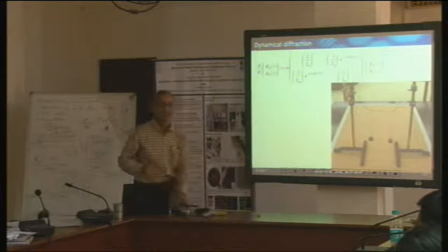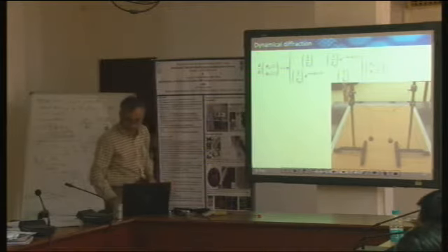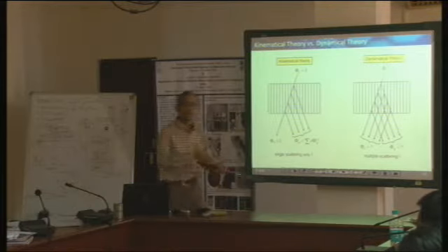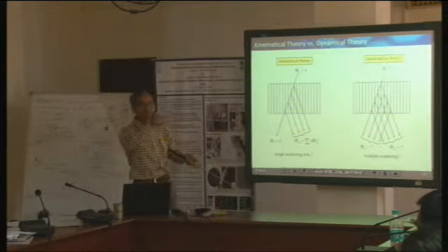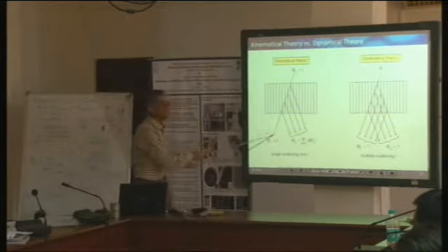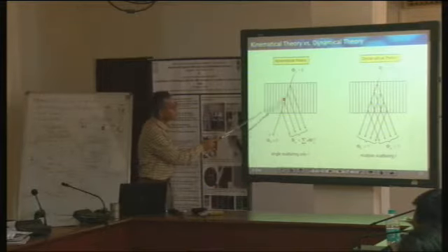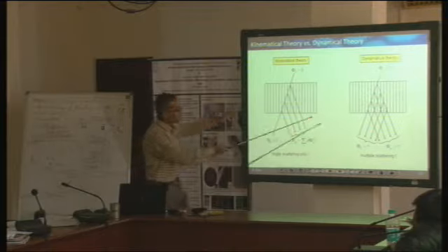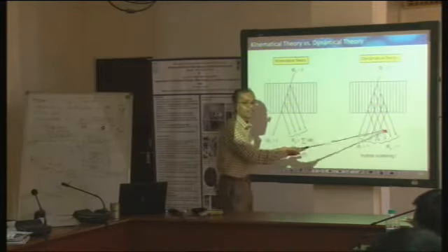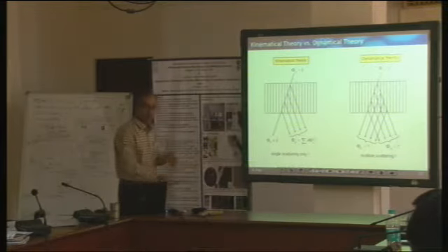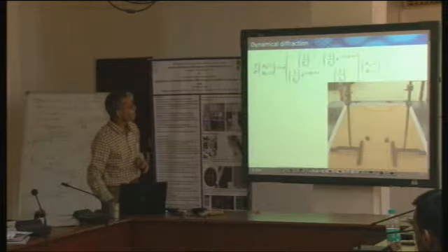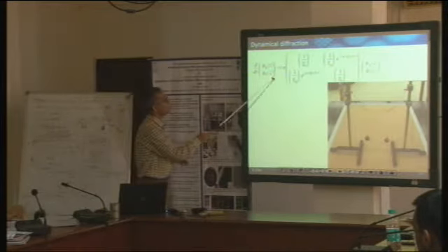So there is some back reflection: the incident beam is scattered into the diffracted beam, but in the dynamical case it is also possible that this diffracted beam can backscatter again. So we have to consider that. That is being solved by these two differential equations.